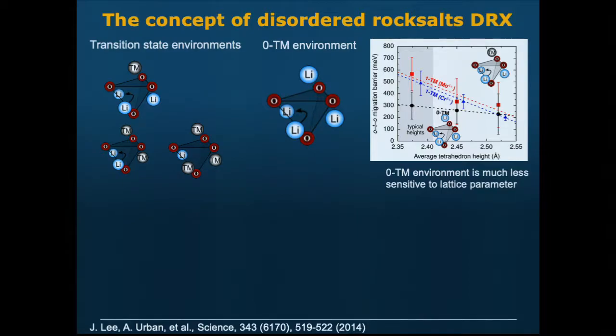And that turns out, if you do ab initio theory, that's what you find. We artificially set up configurations with a lot of these 4 lithiums or 0 transition metal, as we call them. And again, this is now the size of the tetrahedron. If you reduce it, the activation energy goes up only by a little. Whereas if you have 1 transition metal there, it actually goes up a lot more. So the key for us to be able to work with condensed systems that are much less sensitive to lattice parameter change is to create mobility through these what we now call 0-TM channels. And so how do you do that?